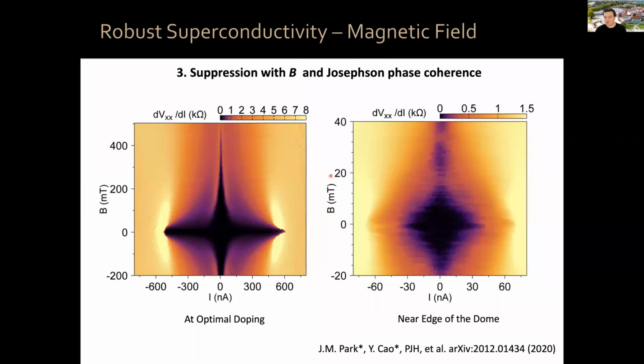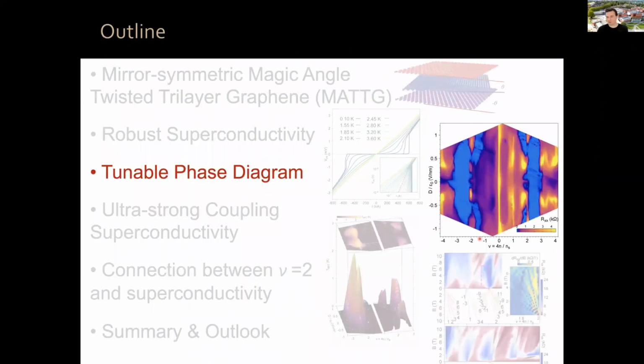And if you go to a region near the edge of the dome, where you know that disorder is going to break up your system into superconducting islands coupled by non-superconducting regions, then you can measure these Fraunhofer-like oscillations. And you have various patterns depending on the random network of Josephson junctions that you have. Okay, so magic angle twisted trilayer graphene is a robust superconductor.